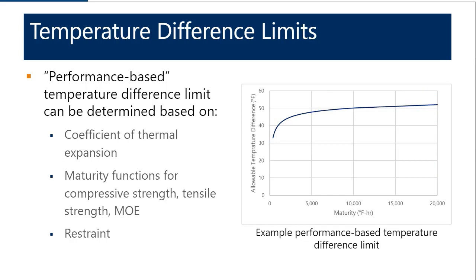These alternatives would be a performance-based temperature difference limit. This is a temperature difference limit that is based on the risk of cracking, and it considers the specific coefficient of thermal expansion of the concrete mixture. Recall I mentioned that certain aggregates will expand more or less than other aggregates. It also considers the maturity of the concrete with respect to compressive strength, tensile strength, and modulus of elasticity, and the degree of restraint. And I'll come back to this maturity in just a second. But here's what an example allowable temperature difference limit might look like based on a performance-based temperature limit. It shows for a particular concrete maturity, again, I'll get to this in the next slide, what the maximum allowable temperature is. And what you can see is that for this particular placement, the maximum temperature can be as high as about 50 degrees without increasing the risk of thermal cracking in this placement.